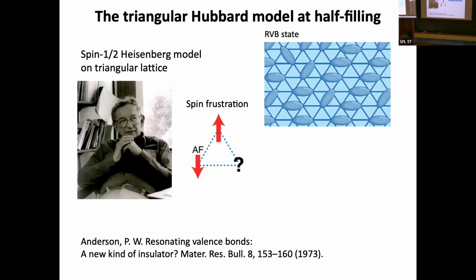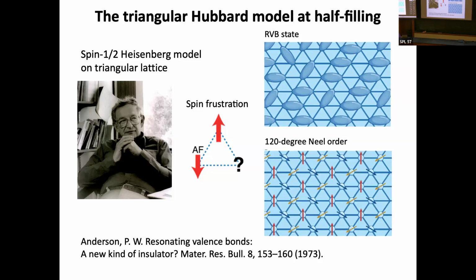So this was the beginning of the field of quantum spin liquids, which is now a very exciting area of condensed matter physics. Like many of the things that Phil started, this was exciting, but it was actually not quite right. So in this case, it turns out that the system finds a way to order the spins in this triangular lattice, and that's by arranging the spins in the plane at 120-degree order relative to each other. So that's what's called sometimes a spiral antiferromagnet. Interestingly, more recent work on the Hubbard model, which is now taking this Heisenberg model but allowing for charge fluctuations, there, people are still studying that, but it seems very likely that in the regime of intermediate interactions, there might be a quantum spin liquid in the Hubbard model. Okay, so the point here is that you can see there's already very interesting physics, even at half filling in the triangular lattice Hubbard model. And things will only get more interesting if you start to dope.